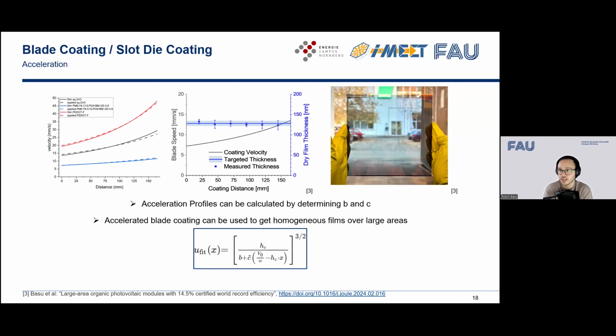So this fit formula can help you, if you know the viscosity and the surface energy, to get homogeneous coatings even over large areas if you use the same geometry as we did. So you need the same applicator. That's also very important. And with that, we can achieve very homogeneous coatings. Here you can see the average thickness over a 16.5 times 16.5 centimeter substrate, and you also see a picture of the coating on the right-hand side. So this works quite well, and it's actually something that can be used universally if you know the input parameters.